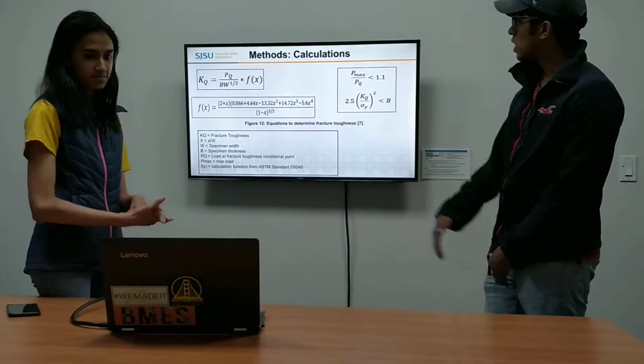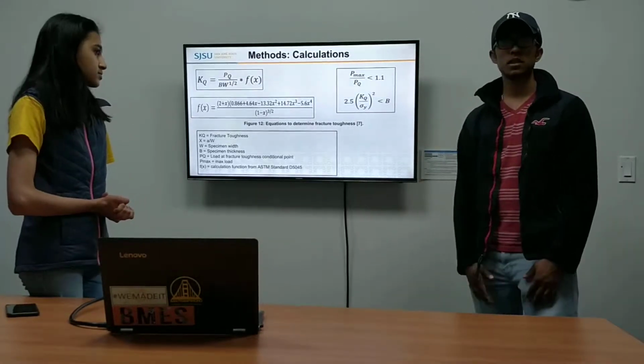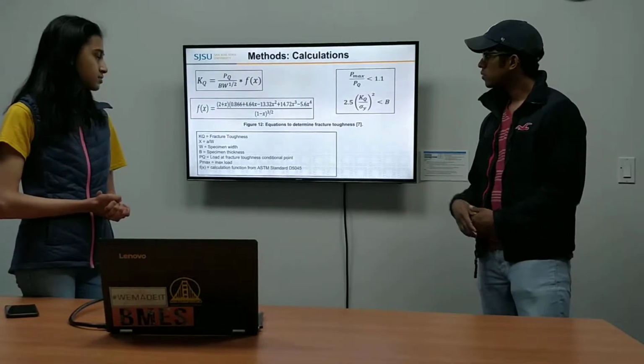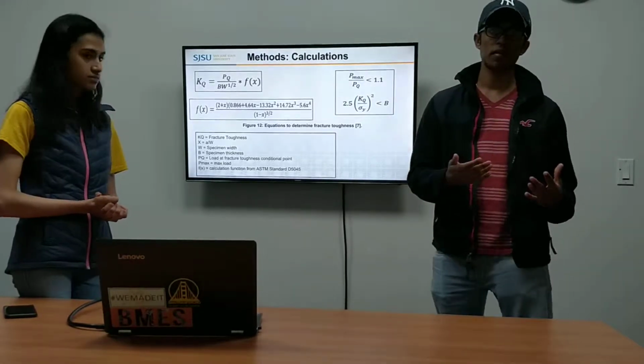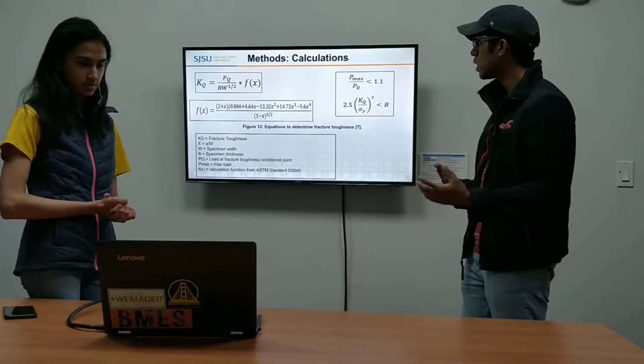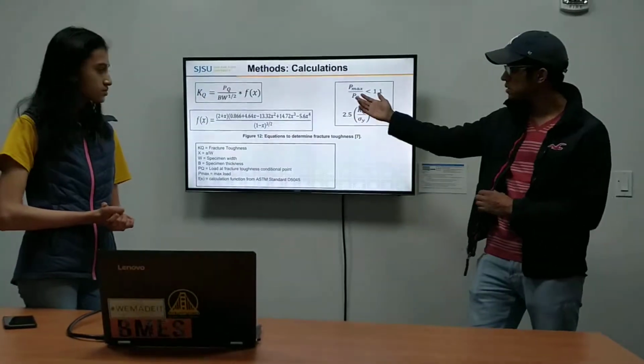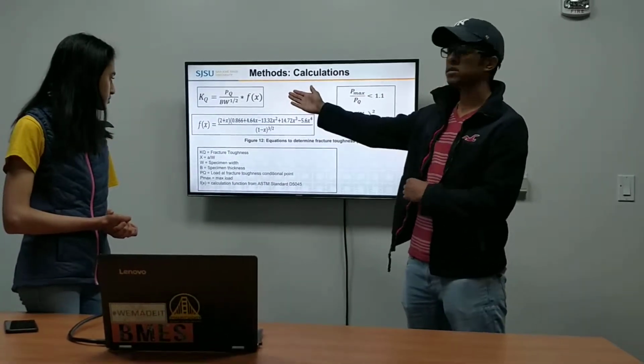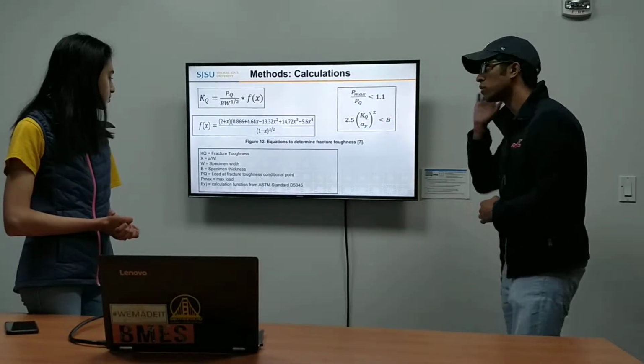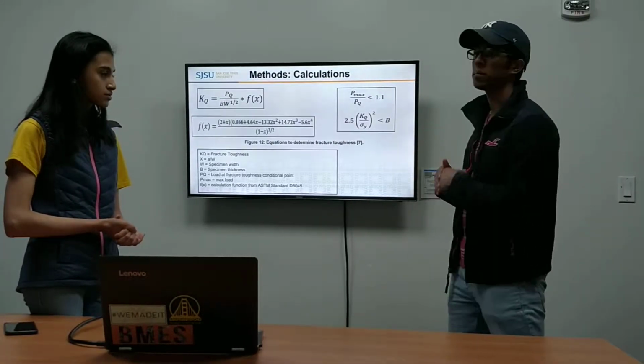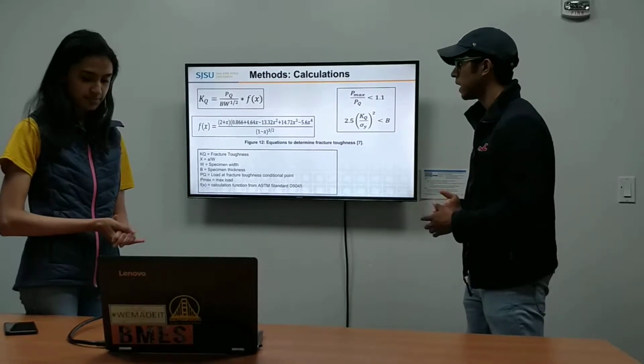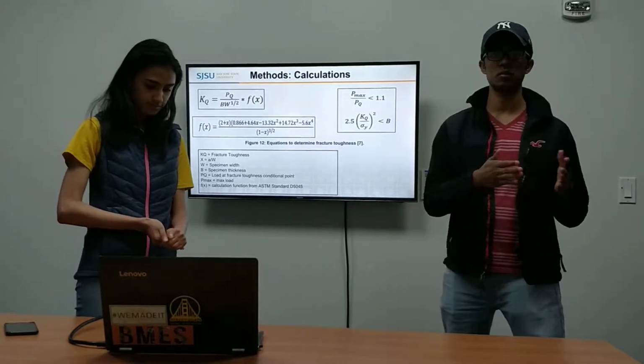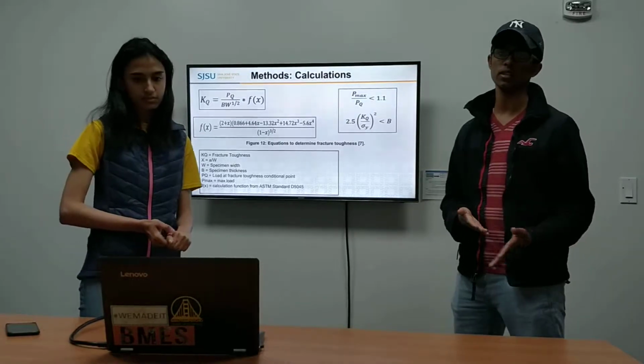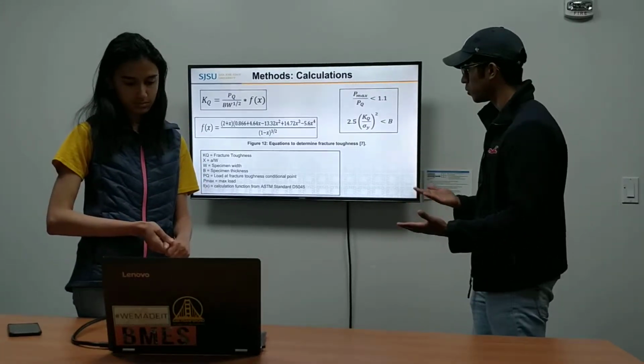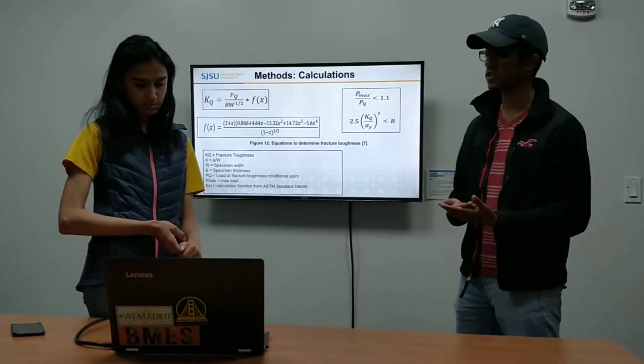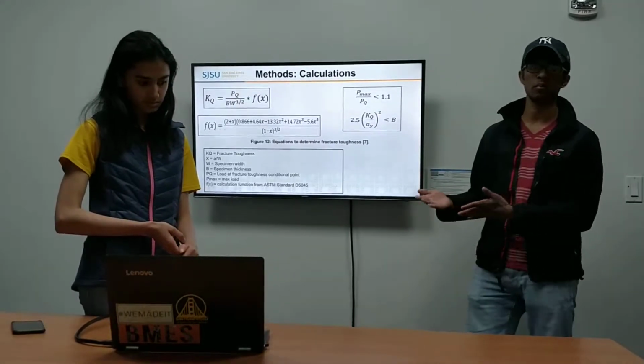And these are the equations. All these equations are found in the ASTM standard that we talked about earlier. Once we get the data from the Instron software, Blue Hill software, we will just calculate these values, and eventually KQ is the fracture toughness constant, and that's what we will finally get, a number to represent each specimen's fracture toughness. We will organize them according to all the parameters like print orientation, print bed location, specimen type, and mechanical setting or balanced set.